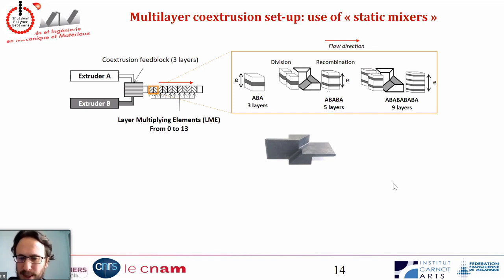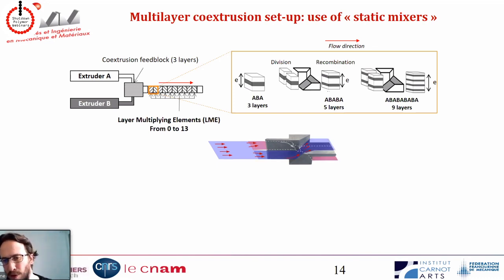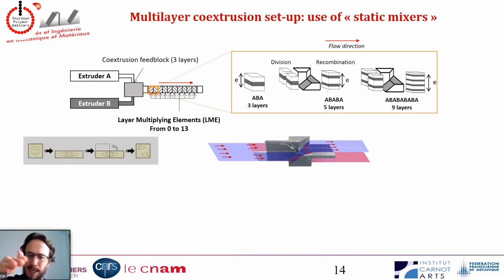And what they will do is they will cut the flow in two. So you see here you have this axe that will play a role like a knife. So it will cut the flow in two. And then you have this little step. One goes up, and on the other side you don't see it, but one goes down. So one part of the flow will go up, and one part of the flow will go down. Then the flow will spread, and then they will merge again. But because it's all in a channel that has a constant thickness, the total thickness of the flow is the same, but you add 3 layers at the start, you have 5 layers after the mixing elements.